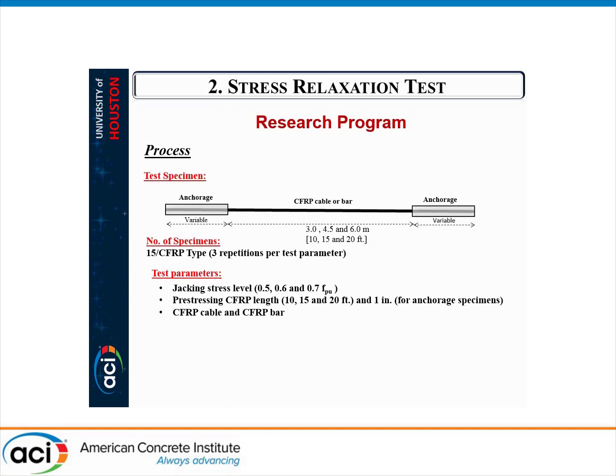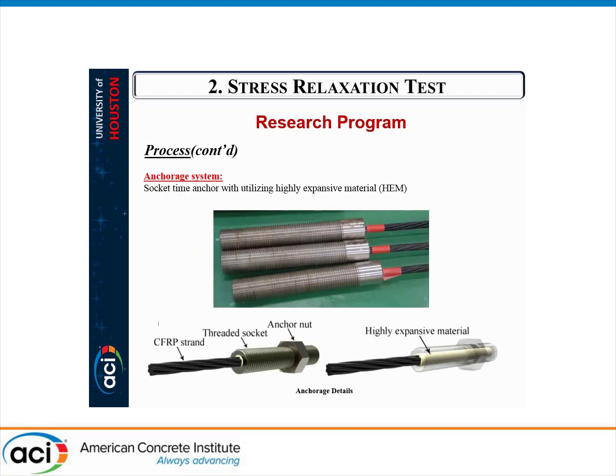So in the research program, we have our test specimens, which are CFRP cables or bars with different lengths and all anchored at both ends. We have 15 specimens per type of CFRP. The test parameters are the level of jacking stresses, which are 50, 60, and 70% of design tensile strength. We have the prestressing CFRP length as another parameter, and also the type of CFRP.